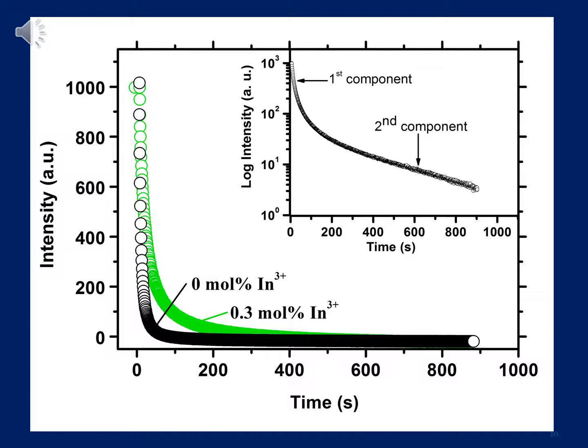Just looking at the decay curves of our materials, it clearly proves to us that incorporation of indium has the effect of enhancing the lifetime of our emission. In the case where we are looking at the decay curve with 0 mole percent of indium, we can clearly see that the decay of the emission is very fast and rapid towards 0. And in the case where we have indium ions, we see that the decay is slowing down towards 0. Now this is an indication that incorporation of indium has been effective in enhancing the persistent luminescence of our material.